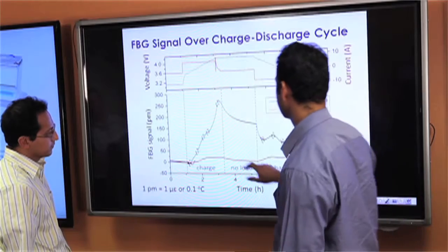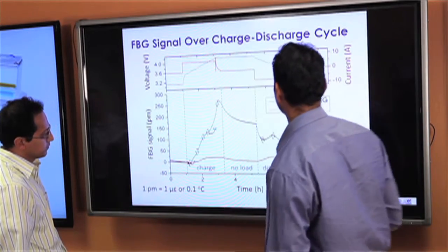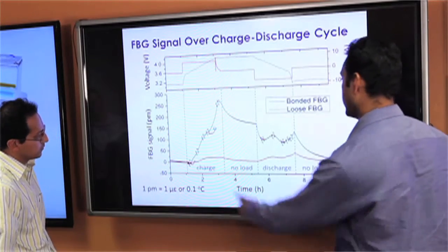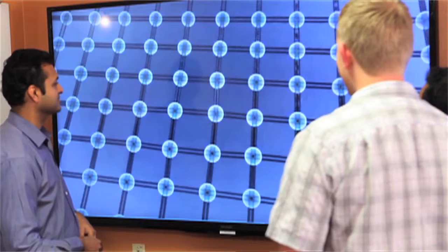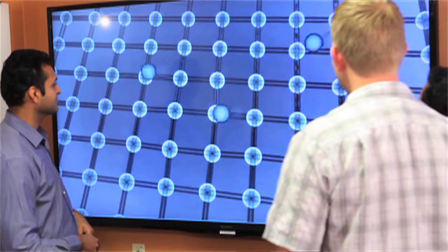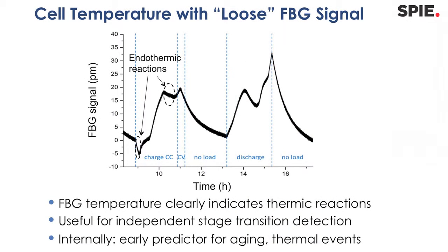And in the case of this battery sensing, most of our current results are based on temperature and strain sensing. And can you imagine if you have lithium ion batteries that are charging or discharging, it means the lithium ions moving from one electrode to the other one, and if they are getting intercalated in this electrode or in this electrode, the electrodes are swelling. You basically can measure the breathing of the electrodes with it. Or you can also see specific temperature changes which occur due to endothermic or exothermic reaction, due to the electrochemical process.